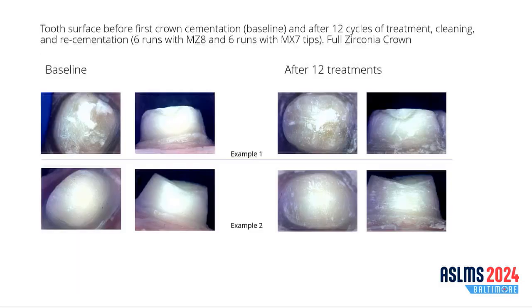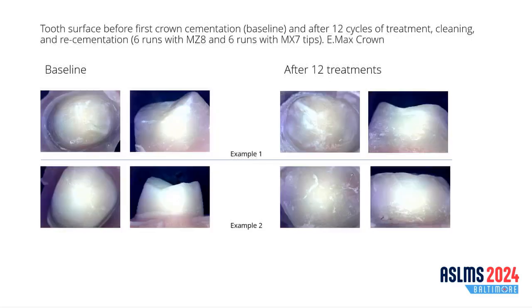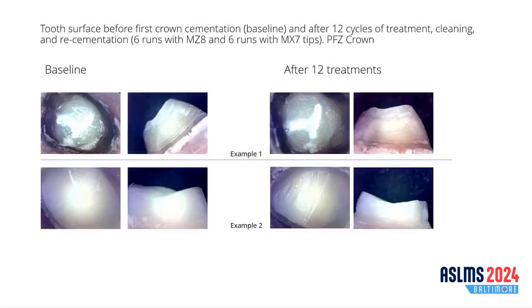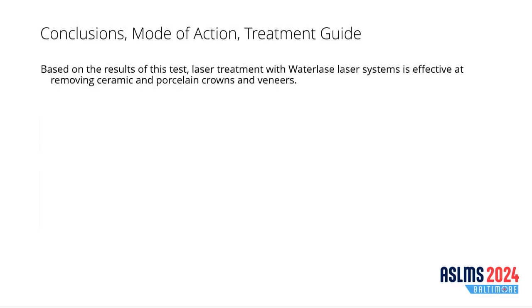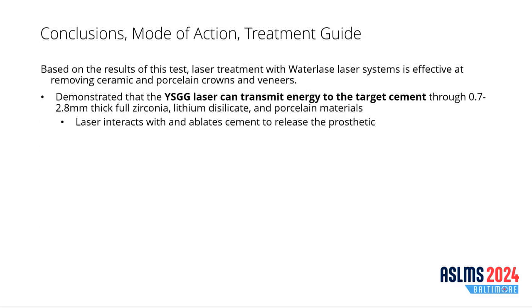The crowns were reused. After removing with a laser, you can reset the crown and reposition it. After 12 repeat cycles, you can see that really the main change to the tooth is just the scratches from the hand scaler. This is after a full zirconia crown. This one is after an EMAX crown removal, and this one is after a PFZ crown removal. So it works with many different materials.